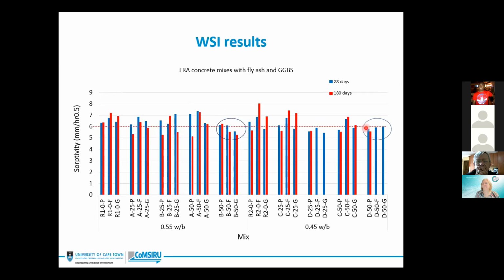This is quite interesting, as it does not agree very well with literature, because literature tells us that it is expected that concrete with a high FRA content will increase porosity and its interconnectedness, and therefore more capillary and water sorptivity. However, this is not the case here.